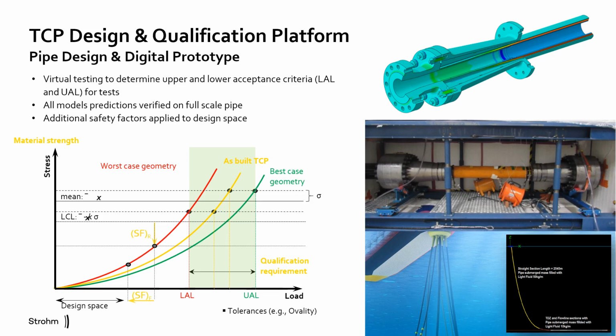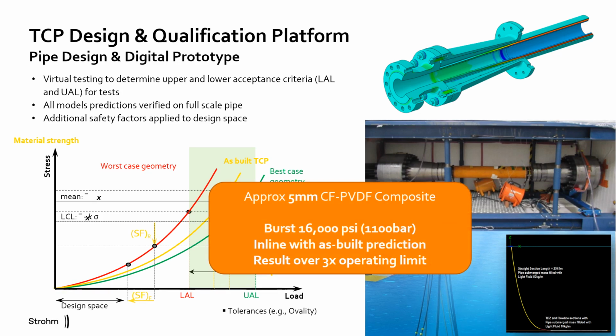As mentioned, the real performance is expected to be in the middle of the upper and lower limit. To give an example, we recently made a carbon fiber PVDF pipe that had a 5 mm laminate thickness. That is, 5 mm made up the structural component that resists the internal pressure, external pressure, as well as the axial tension. Once we completed the pipe, we made a prediction for burst using the as-built geometry. And as expected, the prediction was almost exactly in the middle of the lower and upper acceptance limits.